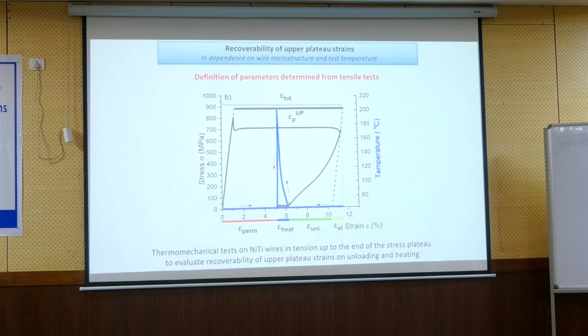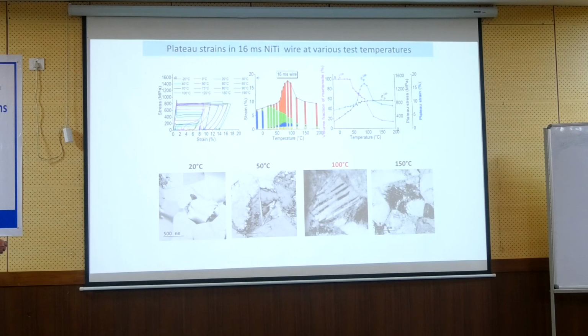here, this is the maximum strain. This strain is the permanent, which could not be recovered by heating. This is the strain which was recovered by the heating. This is the strain which was recovered on unloading, and this is the elastic strain recovered on unloading. Is it clear? Yeah.